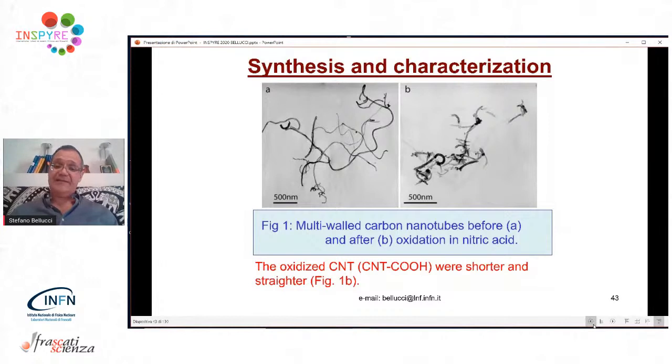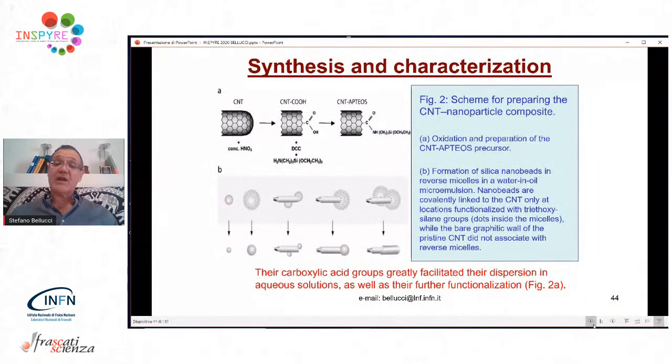Show you here in the early days what we were able to do. These are images from 2003, research published in 2004 by our group, where we started from multi-walled carbon nanotubes, treated them by strong oxidating agents. In particular, here we boiled them in nitric acid, obtained shorter and straighter nanotubes. These are multi-wall nanotubes. We can tailor the morphological characteristics of the nanotubes by adjusting the solution of the nitric acid. And then we grew a nanoparticle of silicon dioxide,